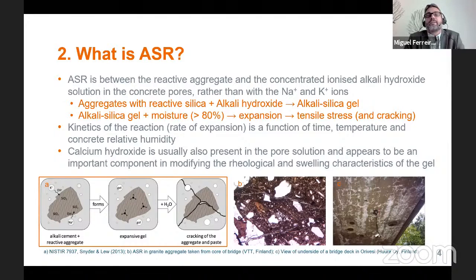And the type of aggregate has a very big role in ASR, and some aggregates can be named as early expansion aggregates, so they react rather fast, like some rhyolitic aggregates, and others are considered late or delayed expansion aggregates. For example, some granites have this kind of performance, and here in Finland we have this type of slow reacting granites. So it might be 40 years before we see signs of ASR in our structures here.